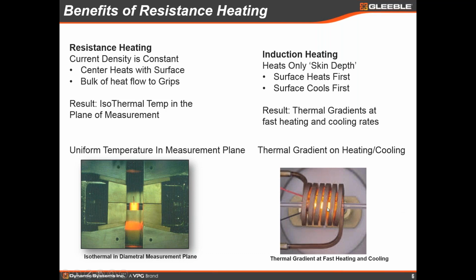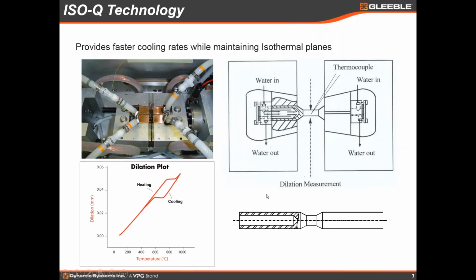Compare that to an induction heater where I'm probably quenching on the outside because I'm not extracting much heat through the quartz push rods here. My surface is going to cool faster. If I quench on the outside, I'm going to cool the surface much faster. The center is still going to be hot. And again, I'm going to get thermal gradients in my measurement that are going to affect the results of my measurement.